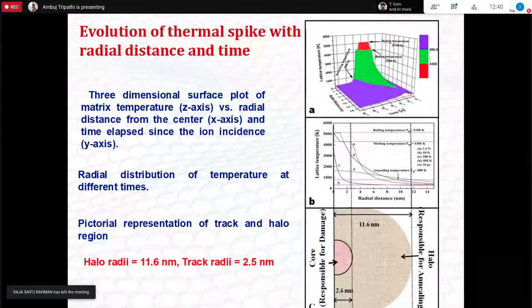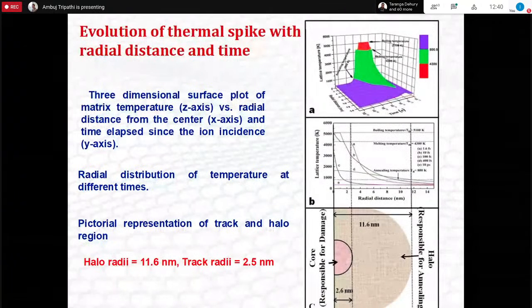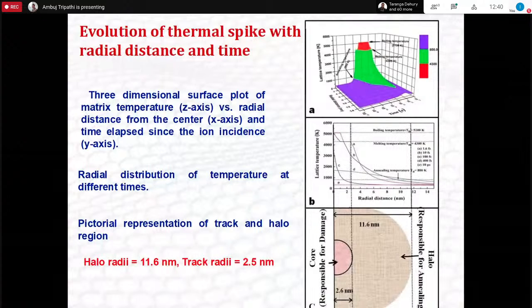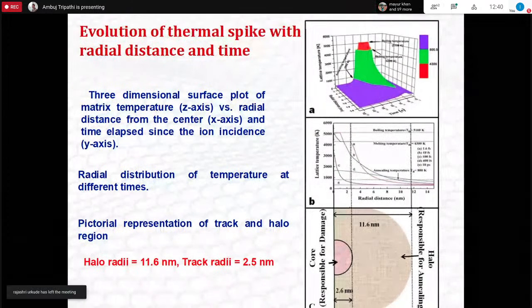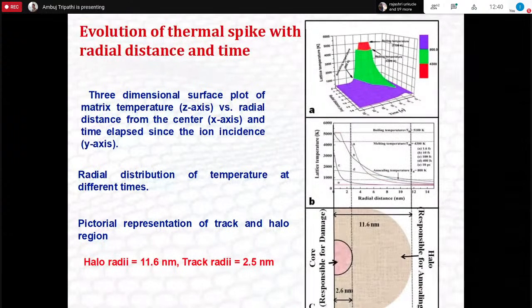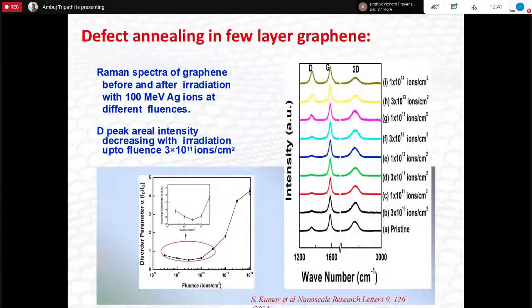So that was plotted, and what we tried to do was define two temperature zones in that. As you see, the temperature goes down radially. Somewhere in the core it will be very high, which will melt the lattice. Somewhere very far away it will be so low that it will not do anything. But in between there will be a temperature where it can do the annealing, meaning the temperature is above what is required for annealing, but below what is needed for melting. So we tried to use this model to get the radii into which these areas can be fitted.